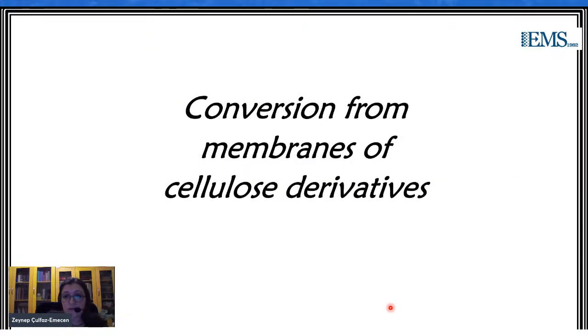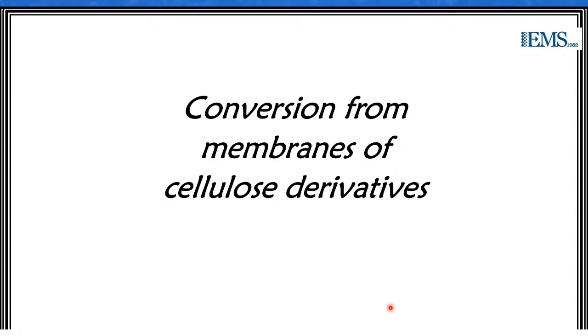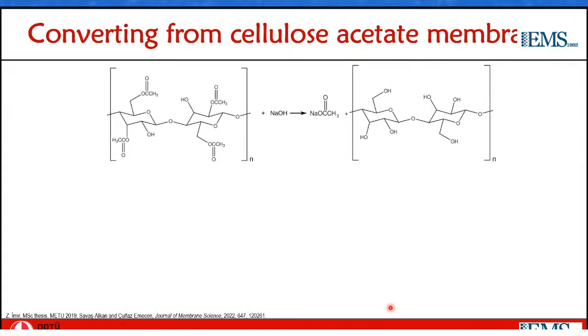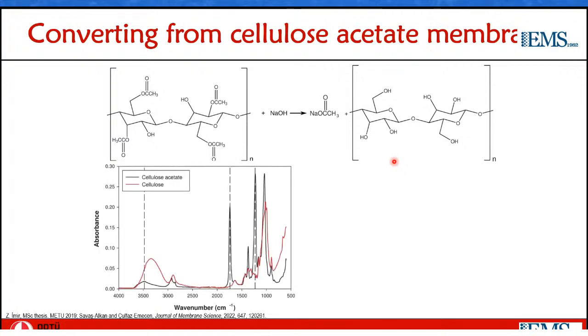A second way of fabricating cellulose membranes is to first make membranes from cellulose derivatives and then convert them into cellulose membranes. A very common example of this is to start from cellulose acetate membranes and then in alkaline medium convert them to cellulose. Cellulose acetate you can dissolve in many different solvents and obtain in quite different morphologies. The conversion from cellulose acetate to cellulose we can watch in the IR spectra by the disappearance of this peak coming from the acetyl group, from the carbon-oxygen double bond in the acetyl group, and then the increase in the hydroxyl band here. So we could do that by varying the alkaline hydrolysis reaction conditions.